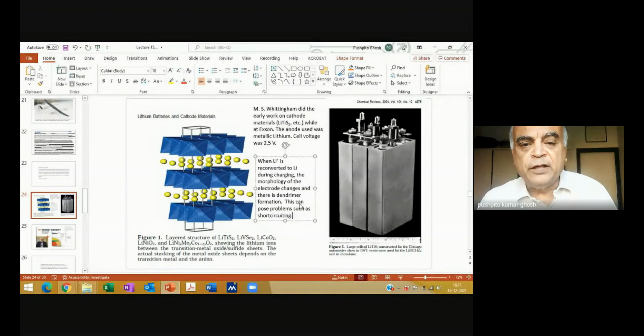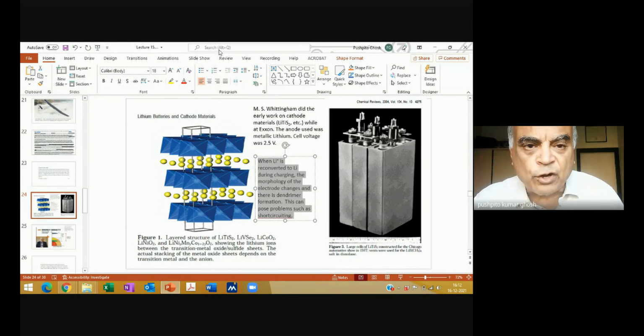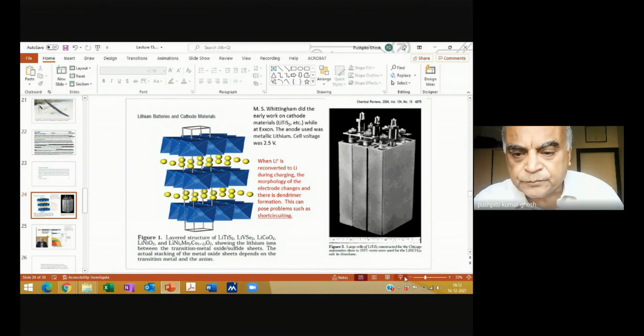Because I started with a nice smooth lithium electrode, but it dissolved, it became lithium ion, and then again it is reforming the lithium. But now the lithium does not form as these flat sheets of lithium. What happens is it forms like whiskers. There will be many, many thin wire-like lithium that will form, and it will protrude out, and it can go and short circuit the cell. That lithium can go and puncture the cathode, and so you can have an explosion. So those were the problems with the lithium metal. But I just thought I'll put it down.